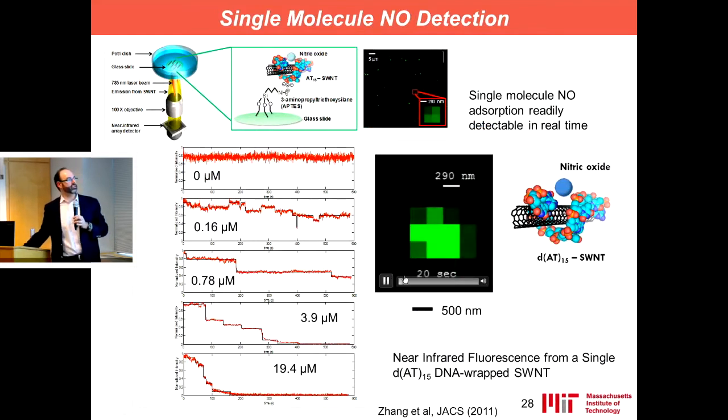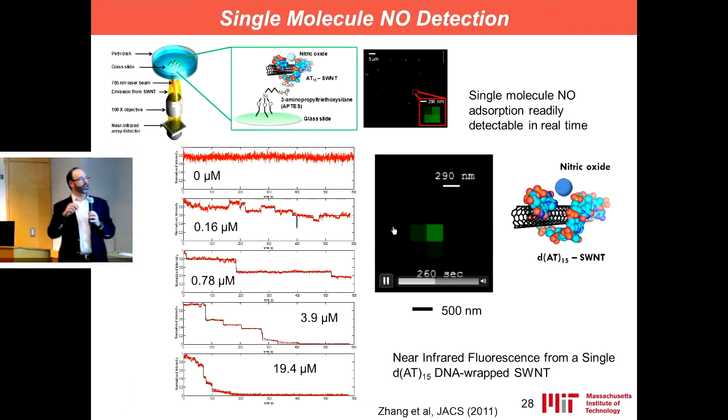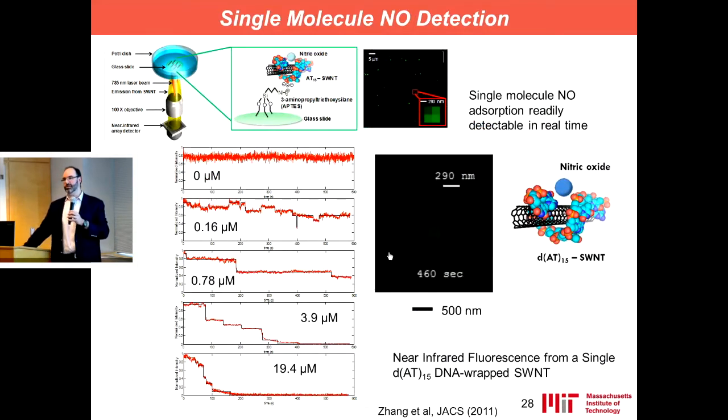So this is a single diffraction limited carbon nanotube. Here is a rod, but you're seeing diffraction. I'm blowing up the pixels, and if you look closely, you're seeing stochastic steps. Those stochastic steps are individual nitric oxide molecules adsorbing to the surface. You're actually seeing this at room temperature in a big messy environment, no quadrupole mass spec trap.